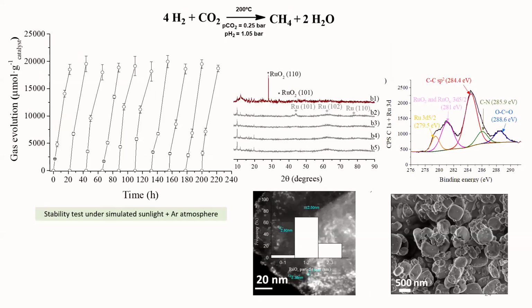We have demonstrated the efficiency of this catalyst by performing 10 consecutive cycles, and the catalyst was almost identical. You can see that the results were very impressive, and we have also characterized it by XRD. The XRD did not show any changes in the structural integrity, and the stability was also confirmed by XPS. And this is the TEM analysis after the catalytic reaction, where there was a slight increase in the ruthenium particle size, but that did not affect the catalytic activity much.